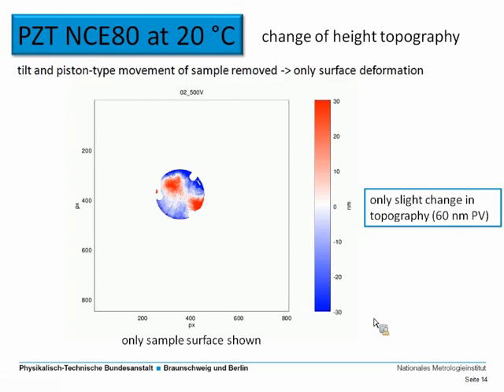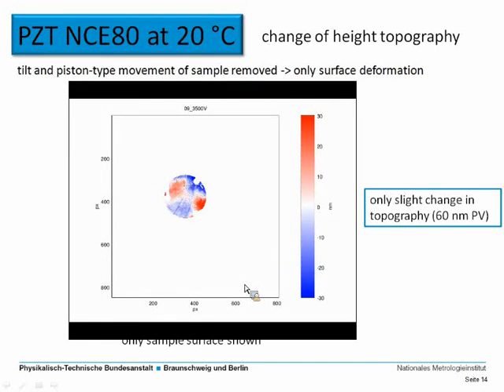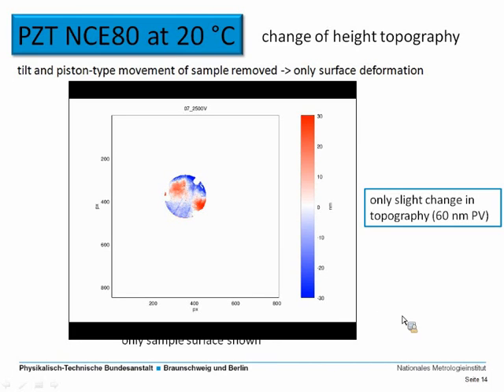And I prepared a small movie where you can see how the sample surface changes when the voltage is changed. So we go up to some maximum value, back down to 0, to negative polarity, and to 0 again, and then you can see that there is some change in the surface shape. It's not really dramatic, but nevertheless interesting that you can see that this kind of change is present. I'll play the movie again so that you can watch it again.